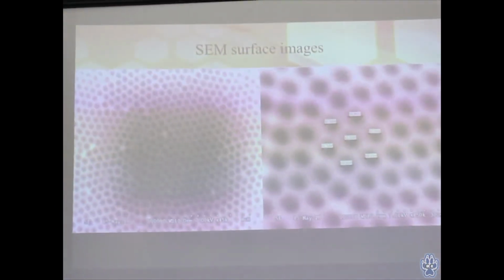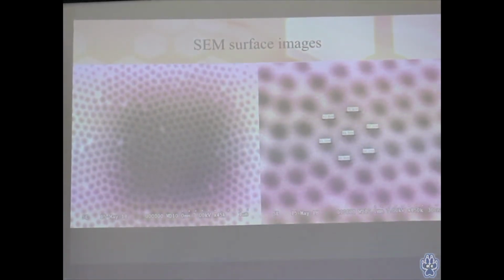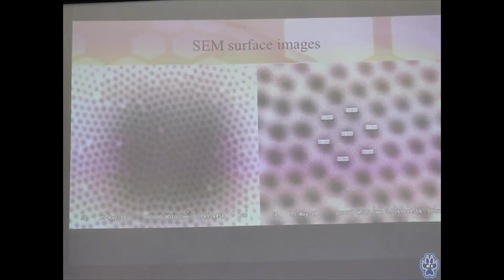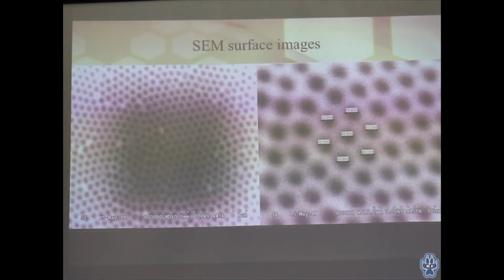And so after we had done this deposition, we took the sample to the SEM to see if we could still see the pores, and we could, which is a really good thing, which indicates to us that we potentially did the electrodeposition and deposited these nickel nanowires without filling up the surface of the sample. And also, we did some measurements to make sure that we weren't closing up the gaps of the pores as we deposited too, and the average is still around 60 to 65 nanometers, which is good.